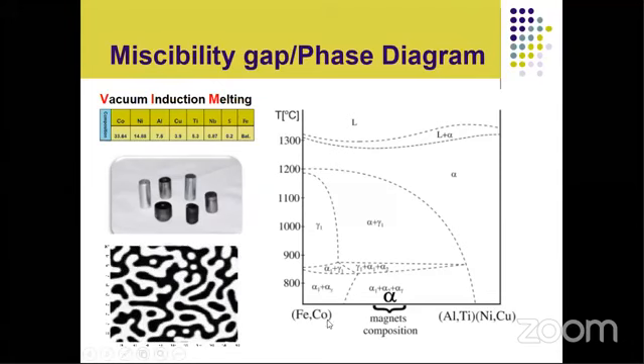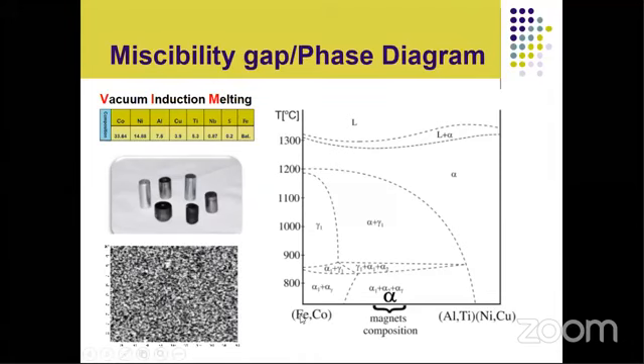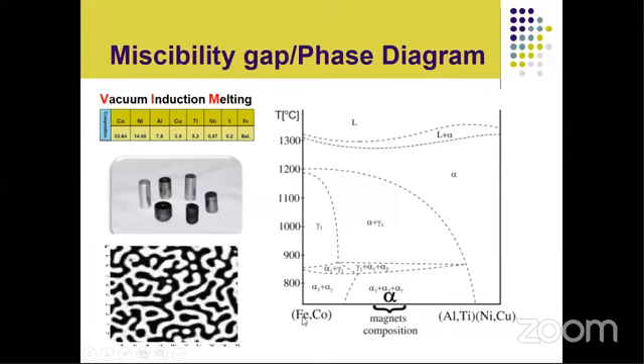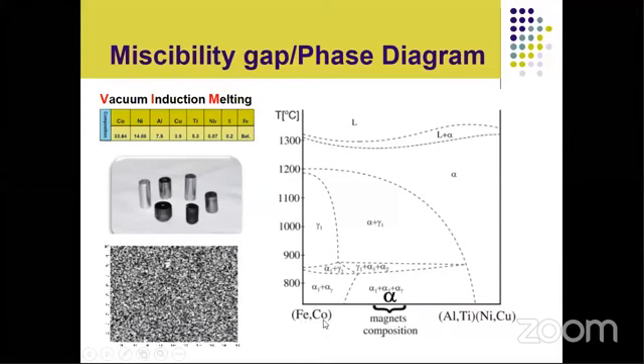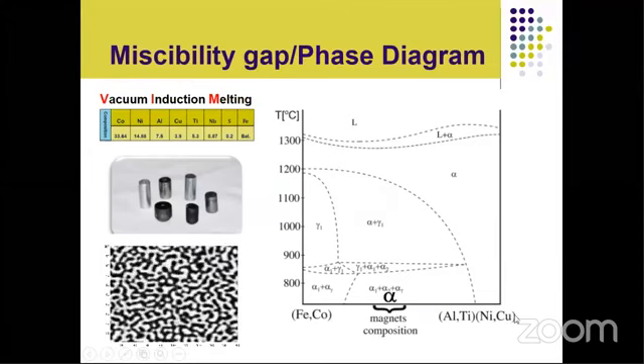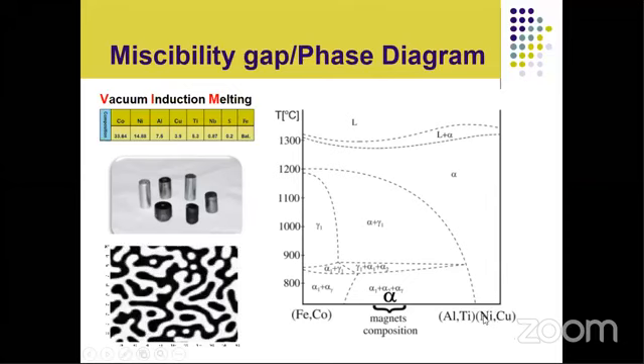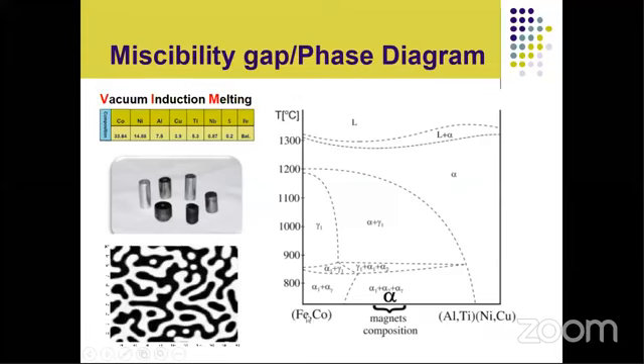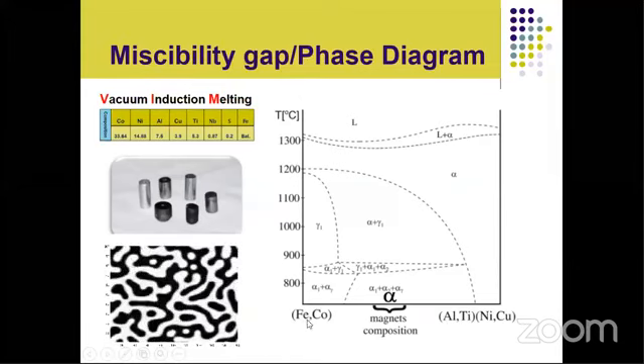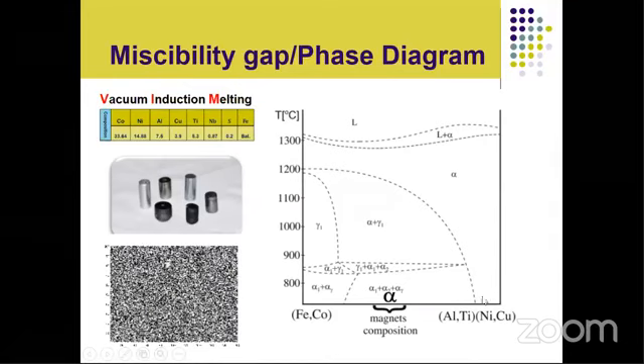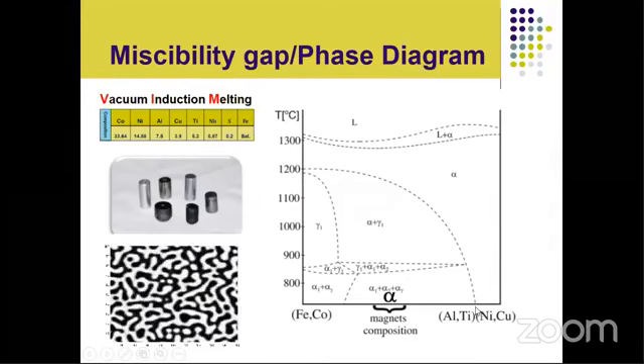But our expertise is this, that we have to make this alpha 1 phase almost pure iron cobalt phase, which may not include nickel and copper, and on the other hand, alpha 2 phase must be pure nickel and copper and other elements rich, but it may not include iron and cobalt, so that it is perfectly ferromagnetic phase, and this is perfectly non-ferromagnetic phase.